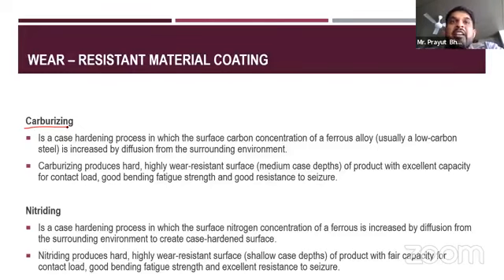It produces a hard, highly wear resistant surface material, with excellent capacity for contact load, good bending fatigue strength, and good resistance to seizure. So basically, carburizing, as you can see from the word itself, involves a low carbon material. There are certain steels we have to produce in a low carbon concentration to have good ductility and all those things. But to achieve surface hardening, we need a higher carbon concentration. So this is the process that we use for increasing the carbon layer on the surface, and that way giving better wear resistance. It's not as good as a surface coating by a composite material or an altogether different material, but it serves the purpose at low cost.